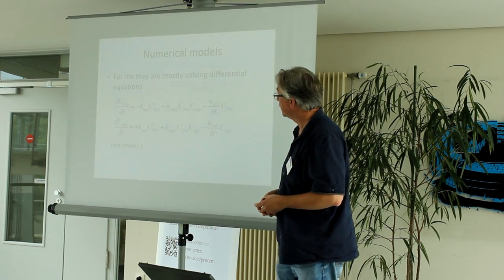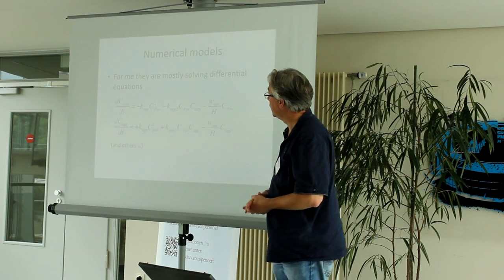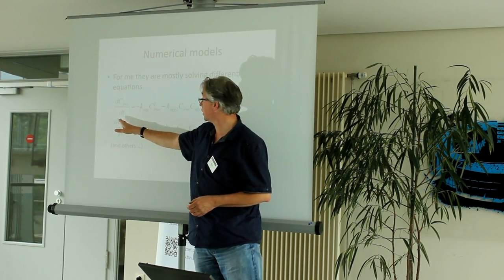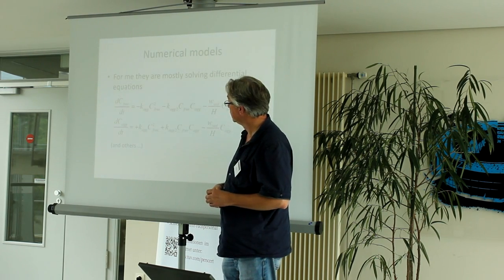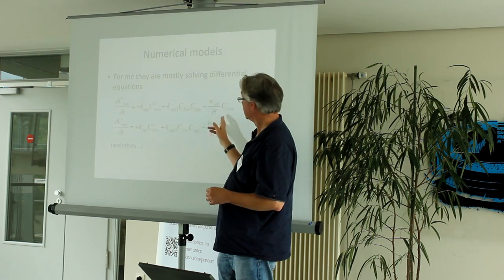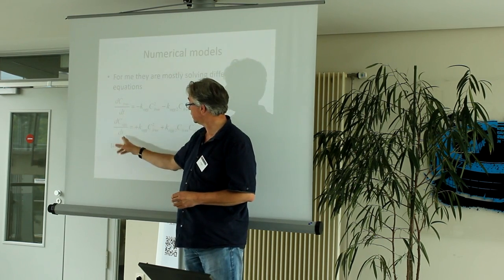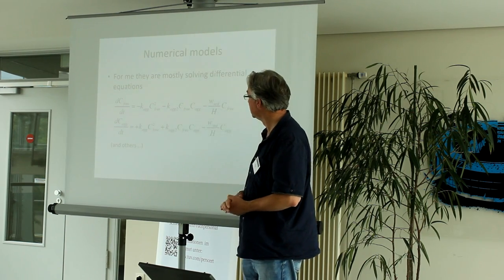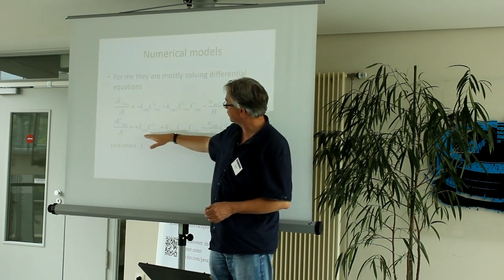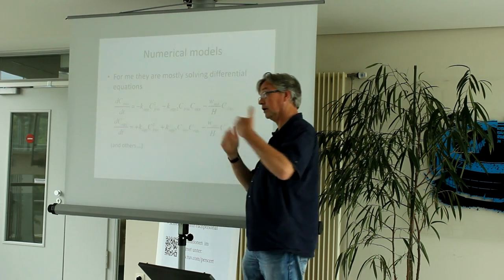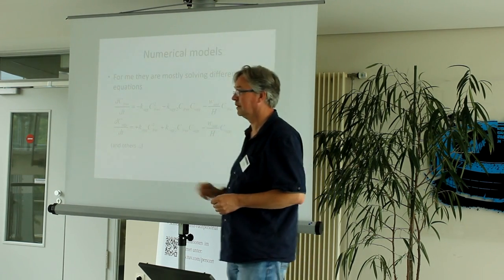Well, I mentioned numerical models, just to tease you a bit. Here's a small example of the sort of equations I solve. This one represents the concentration of nanoparticles, and I have two terms for the aggregation processes that take place, and there's a third one to describe how fast these particles will settle to the bottom. This is another parameter, the concentration of aggregates of nanoparticles, and where this is being taken out of the free concentration, that goes into the concentration of aggregates, and that way you have a closed mass balance. This is another reason to look at masses rather than surface areas. It's easier.